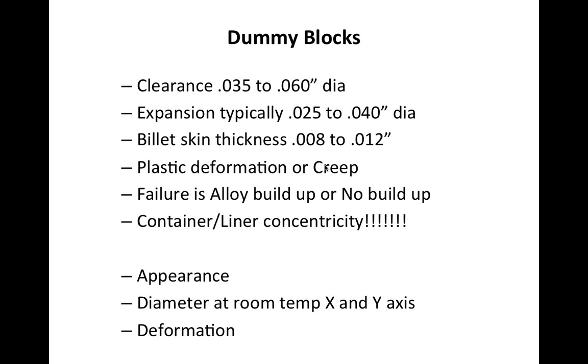We would like the dummy block to expand to the 25 to 40 thou and come back to as close as nominal for as many times as possible. And by doing this, then you can extend the life. One of the biggest problems in dummy blocks today is container liner concentricity. If your liner is bellied, your dummy block life is going to be minimal. If your liner is overexpanding so that you have high pressure or a very long billet, you have to make these containers typically in 3 pieces to manage the mechanical expansion of the liner at temperature.